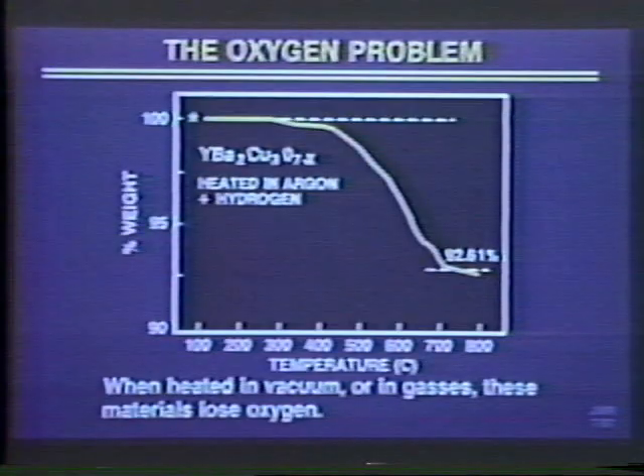Now, let me come to what I see as the first real processing problem, which is novel to these materials. On the next slide, the oxygen problem. If you heat these materials in vacuum or in gases other than oxygen, they will lose oxygen, and you've already heard what effect that has. This is an extreme case that I've shown here in that we heated one of the 90 degree materials in argon plus hydrogen, which of course reacted with the oxygen. But the results might be somewhat similar if we just heated this film, this bulk material, just in argon alone.